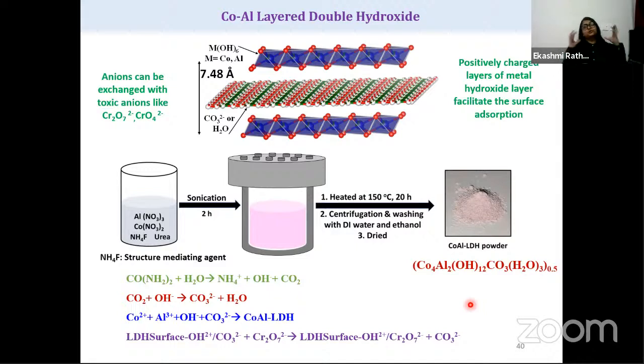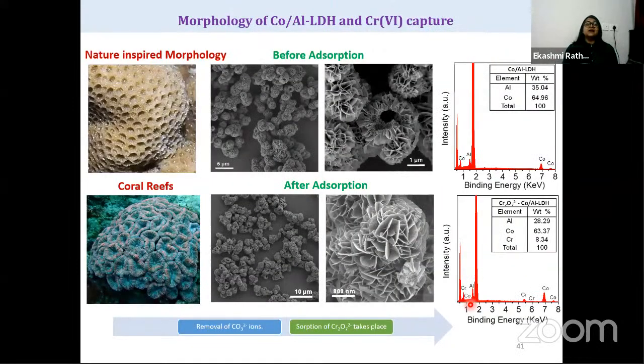I wanted to look at this at the micrometer scale. So I did scanning electron microscopy imaging, and here you can see that this material has a beautiful structure, which looks like the coral reefs we see when we are scuba diving or visiting water bodies. From this experiment, I figured out that before and after adsorption, there is no morphology change, and here you cannot see the chromium peaks, and with chromium adsorption we saw the peaks of chromium coming. So it tells us that there is removal of carbonate ions, and adsorption of chromium is taking place.